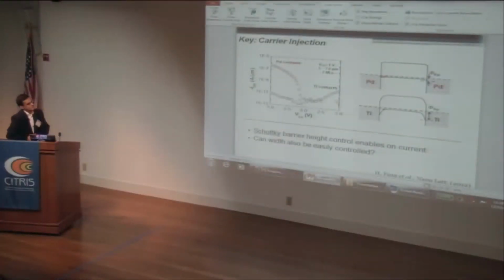We all know the importance of contact resistance. And to answer this, we started looking at different metal contacts. We just started using metals with different work functions. These are p-type devices. By using a higher work function metal, you would presume that you can form a lower Schottky barrier height to the valence band.